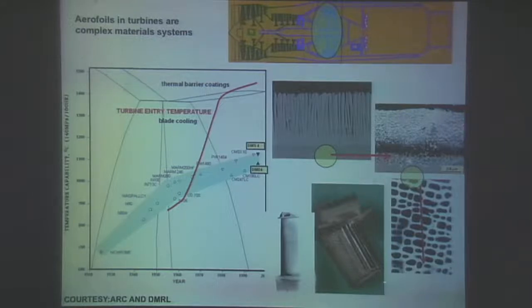So these parts that see the highest temperatures are all internally cooled, okay? So here is the external part, and if you break it open, it's actually a thin-walled part which has intricate channels for airflow through the part to provide internal cooling, okay? So blade cooling is one way of increasing the temperature capability. The other way of increasing the temperature capability is to provide insulating ceramic materials on top of these blades, so thermal barrier coatings. So this material system is not just a single material. It's a thin-walled, precipitation-hardened, nickel-based superalloy with oxidation-resistant coatings, on top of which are thermal barrier coatings.